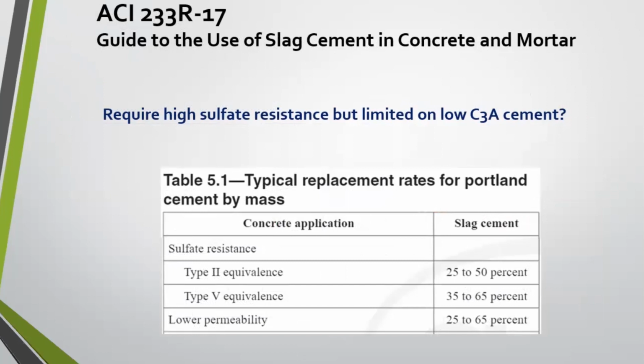This is just showing you rules of thumb. Let's assume you're in an area that has high concentrations of sulfate in the soils or in the groundwater, but you're limited in the cements that you can purchase. Let's say you've got a type 1 cement with a high C3A content, and you still need some level of sulfate resistance. These are just guidelines. Basically, if you want a type 2 equivalence, you'd need to add 25 to 50% slag. Type 5 would bump up to 35 to 65%, and so forth and so on.